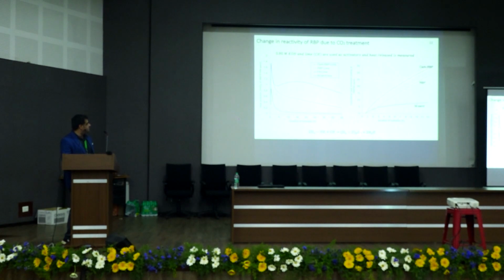And then we compared the total amount of heat generated as a result of this change in reactivity. And we see that in 12 hours from the addition of the solution, carbonated brick powder shows much higher heat release compared to non-treated brick powder. Sand is somewhere here. Sand is mostly inert, but due to the presence of KOH, some silica can be etched and can go into dissolution and react.